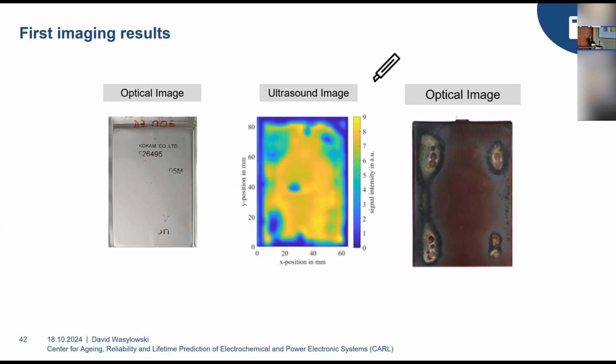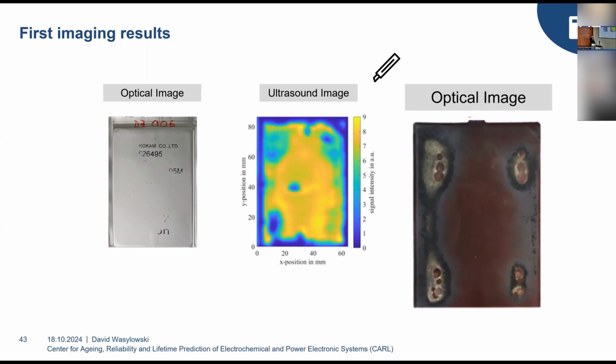But if we take a closer look at one of these deposits, they seem to be surrounding this inhomogeneity here, so these round brown circles here. And this is really interesting to us because we earlier hypothesized that those really strong aging effects that we want to prevent within battery operation are coming from local design flaws or inhomogeneities. And we talked to a bunch of manufacturing people, and they confirmed to us that this is most likely due to a not optimally performed Z-folding procedure.